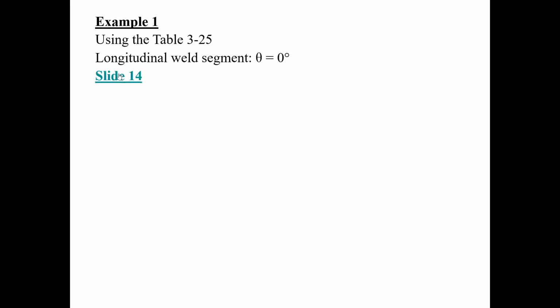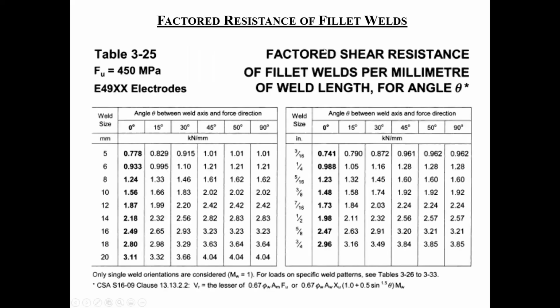Now, let me show you what we do with the tables. We'll use the tables, so this way you'll see why I like the tables versus the equations. The longitudinal weld at 0 degrees. We go back to the table. We said we had an 8 millimeter weld, and the orientation of the weld group is at 0 degrees. Therefore, the resistance per millimeter weld is 1.24 kilonewtons per millimeter.